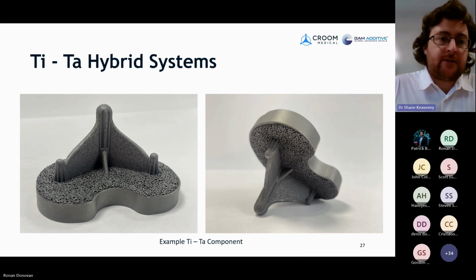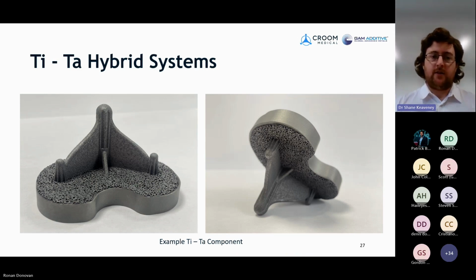The other part to mention, which Patrick discussed at the end of his section there, is this idea that we've been working with on the combination of materials. So as I mentioned, one of the issues with tantalum, well, there's a cost piece, there's also a weight, which is more the concern. So the weight of the tantalum is 4 times that of titanium. So if we're working with solid tantalum component here, it could be quite heavy. And we feel that it might be more appropriate to use the tantalum specifically where we really need it. And that one area is really the osteoconductive structure, this porous structure. So we have here demonstrated the printing of tantalum onto titanium. So we have a titanium base plate here that we have printed the tantalum onto, and then post-machined this lower section for the various features.